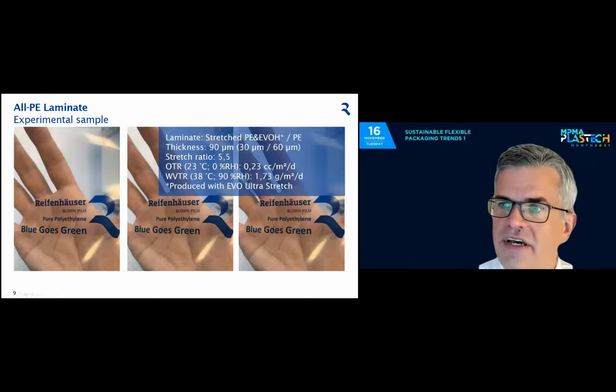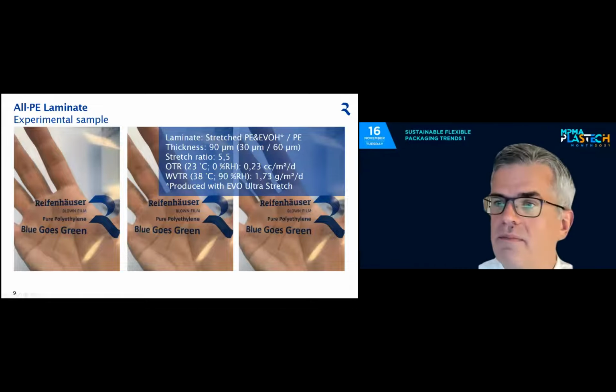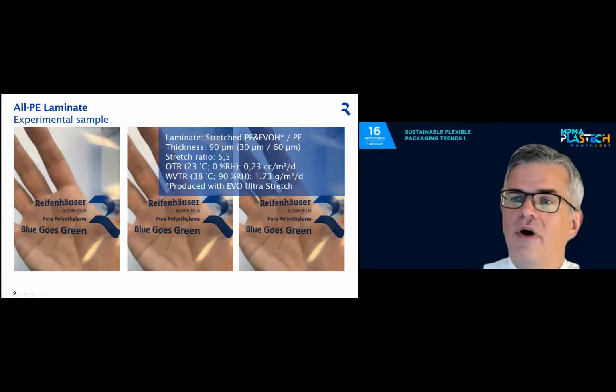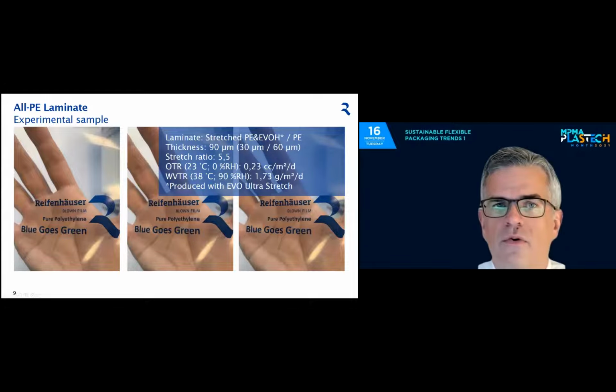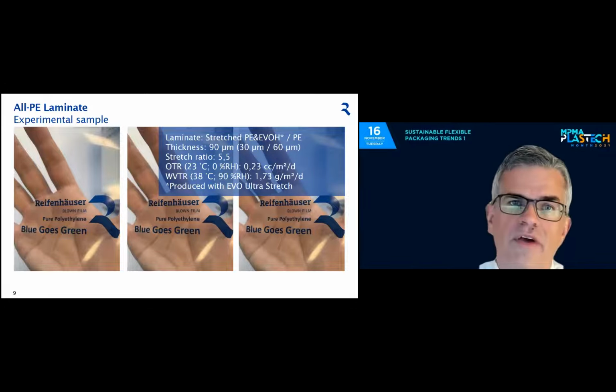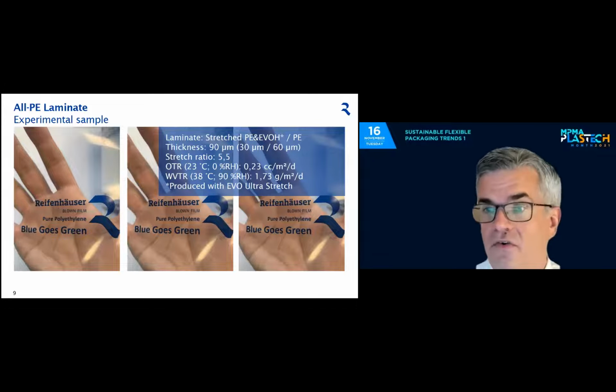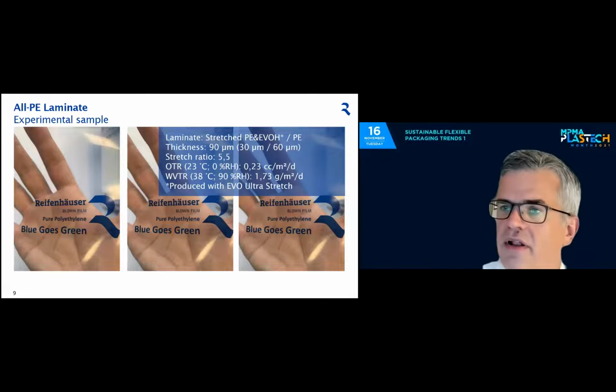And the stretch ratio of a stretched film of the PE EVOH 5-layer film was like 5.5. And we were able, by doing so, to reduce the oxygen and the water vapor transmission rate: for the oxygen below 1, but for the water, we are still well above 1. So the question comes up, what can I do if I need even better water vapor transmission rates? Well, very simple,